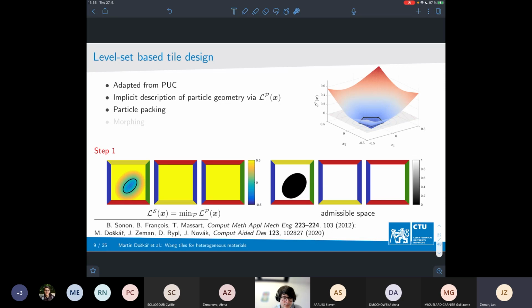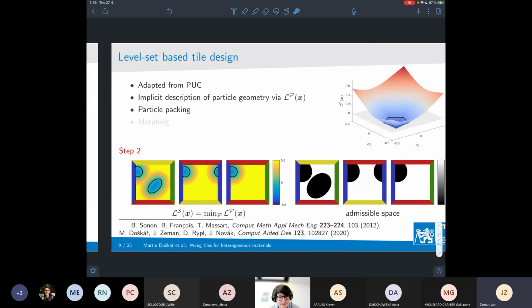This is the associated level set function or signed distance function. And by thresholding the zero value by a certain constant value, we have the position which is prohibited for the placement if we would like to avoid overlapping of the next particle. And because in this case we were lucky enough to throw the particle inside the tile, nothing is needed, and we are doing exactly the same step as in the original approach.